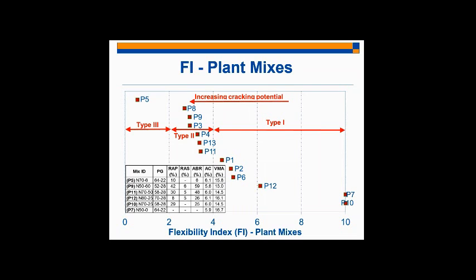And so let's, for example, look at P9. So P9 is a mixture with 59% ABR, resulting from the combination of 42% RAP and 6% RAS. So that's a lot of asphalt binder replacement. And the AC content for this mixture is 5.8, right? So I can see that this mixture falls on the left end of the spectrum towards the poorer performing mixture side. And so as you move towards the left, you have increasing cracking potential.